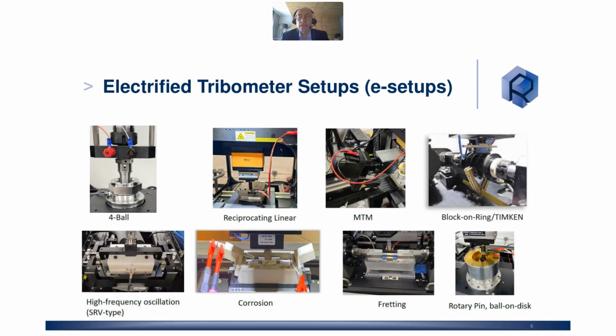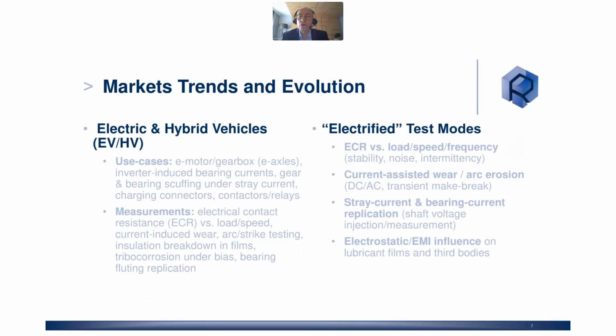The interest behind that is that there is a lot of need in industry for doing tribology testing with electrification. Of course, it comes from electric vehicles and hybrid vehicles, where you would like to test a gearbox or e-motor, where there might be stray current remaining, and that influences the wear resistance of different materials. The combination of lubricant with material in the presence of stray current might influence the wear resistance of the material. Therefore, having options like electrical contact resistance combined with the possibility of tribology testing with load and speed gives you a good insight into laboratory testing in different kinds of conditions.